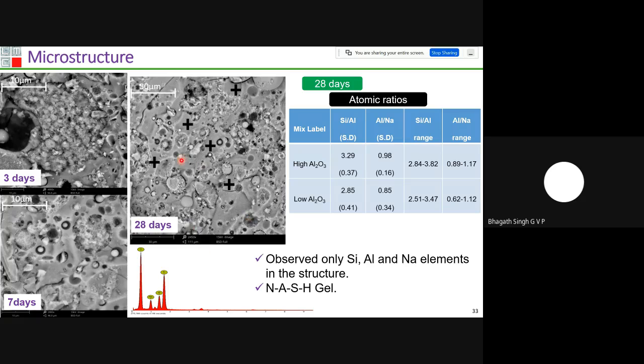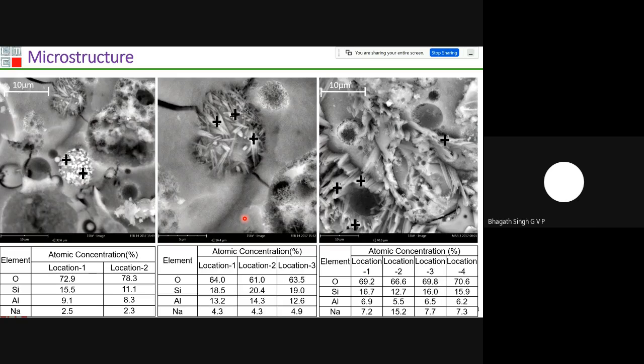And if you look at these results here, I have tried to identify what elements are incorporated in this reaction product, and at all these locations, the silica, alumina, sodium elements are incorporated. Finally, I have classified it as sodium alumino silicate gel. Then I have also observed some new crystalline phases during the product formation. What are those crystalline phases?